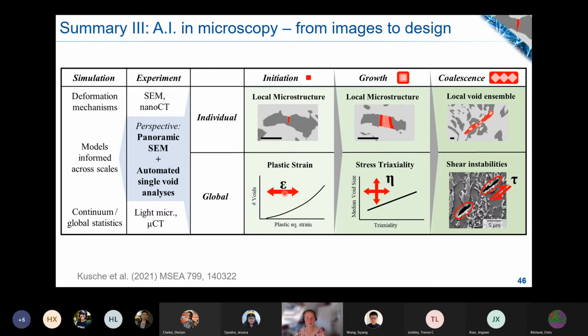And one main insight that we found here really was that all the classical damage models that we have were actually derived on model materials which had one metallic phase and were fairly isotropic. And what we found was that, of course, in a material where we, for example, combine ferrite and martensite, that locally doesn't hold true. Locally, you're dominated by the local stress state. That's why you need the 3D information as well. But overall, if you look at many damage sites, then you find what you expect in a global image. So these models seem to still hold, so we can use them in the process simulation. That, for example, plastic strain is what actually drives nucleation of damage, and the triaxiality, so the overlaid hydrostatic component, is what seems to drive growth of all of them.